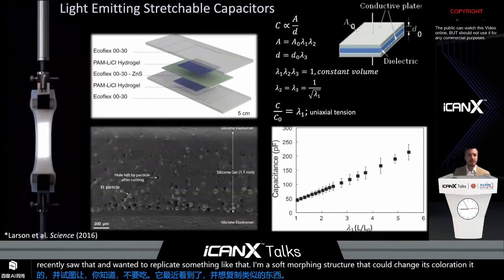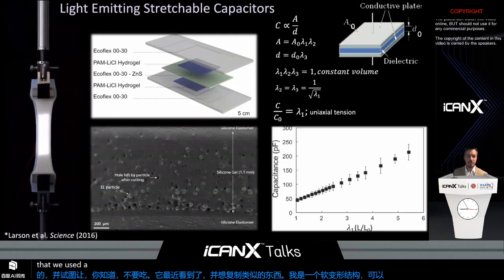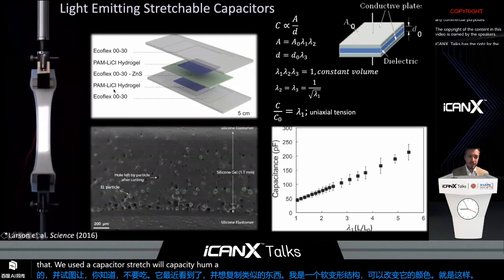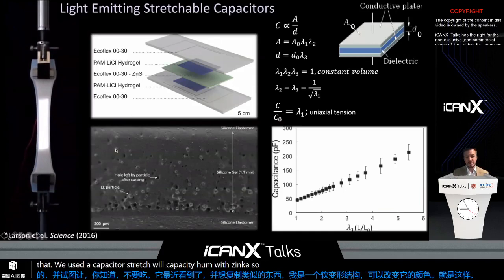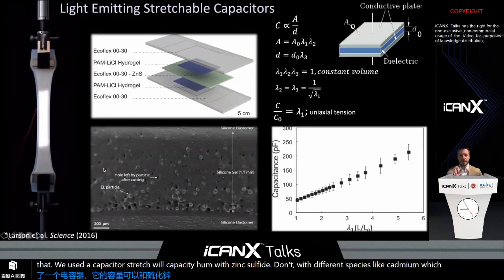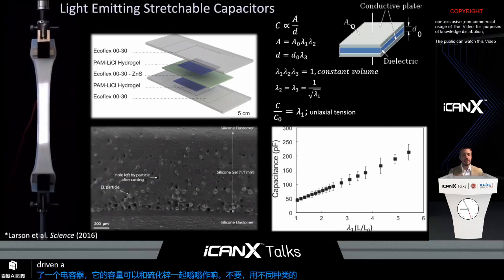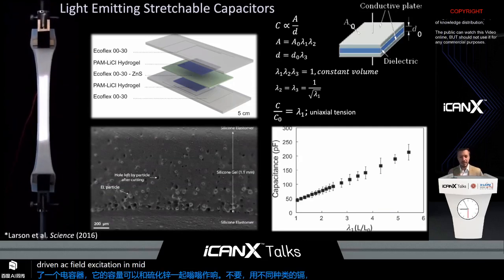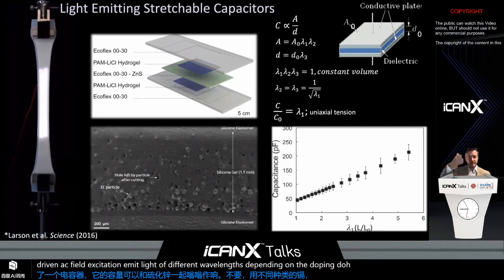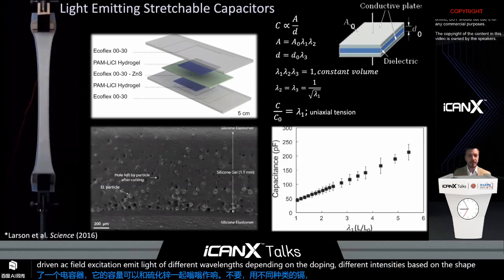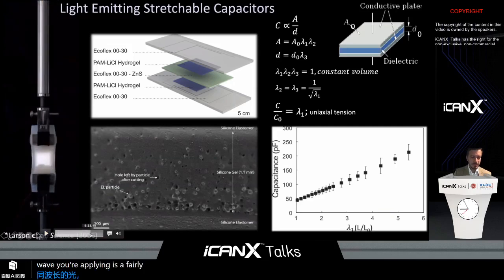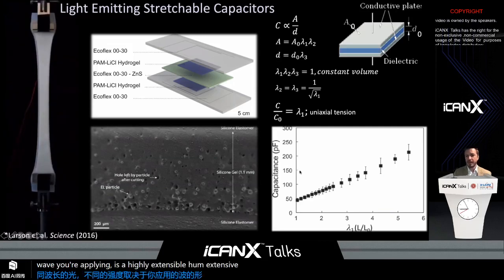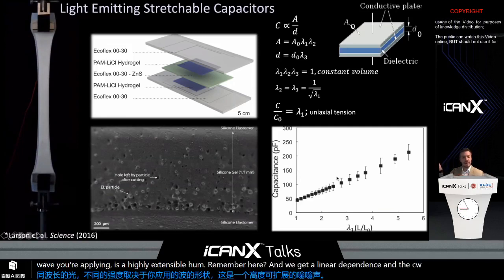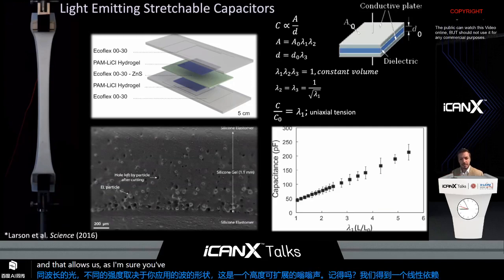And so to do that, we used a capacitor, a stretchable capacitor, with zinc sulfide doped with different species like cadmium, which will, under an AC field excitation, emit light of different wavelengths depending on the doping, in different intensities based on the shape of the wave you're applying. This is a highly extensible rubber here, and we get a linear dependence of the capacitance as we stretch it. And that allows us, as I'm sure you've seen in other talks, to self-sense the deformation while displaying this information.